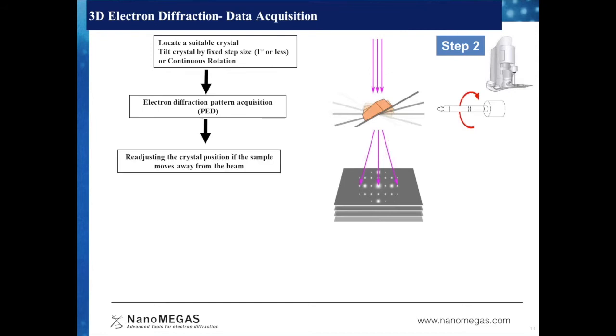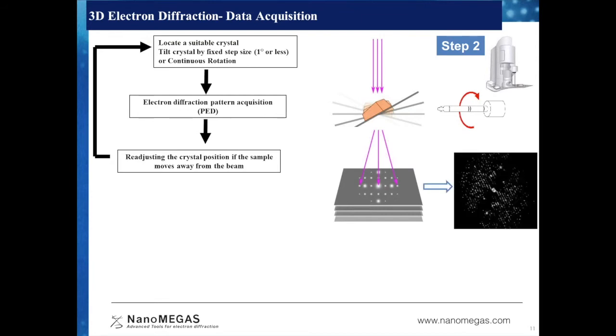During the tilting process, usually the sample moves away from the beam, then we readjust the sample manually, and once this data acquisition process is finished, we obtain three-dimensional electron diffraction data. The data acquisition process is usually highly reproducible and robust. Sometimes the acquisition time is very short, close to minutes, but sometimes it takes hours depending upon how challenging the sample is.